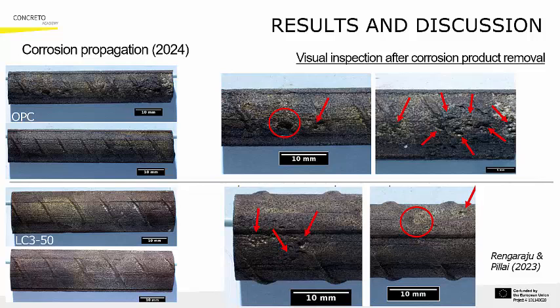Corrosion propagation was further analyzed after cleaning the rebars. Images also taken with an optical microscope show the true extent of the damage. As can be observed on the rebar from OPC concrete, the pitting is denser and pits are deeper and wider, indicating advanced localized corrosion that affects large areas of the surface, giving the impression of a general corrosion.